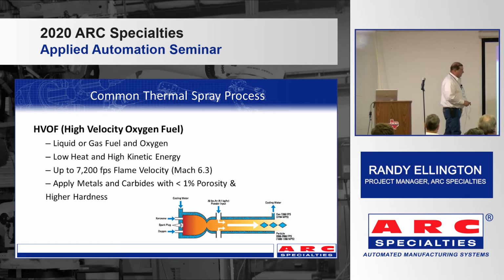HVOF tends to have low heat, and that's a relative term because it's still hot, but it's much less than like plasma. Where that's good is applying stainless steels and Inconels, your corrosion-resistant alloys. You're not over-oxidizing. Same with your carbides. You're not oxidizing the actual material. On the other end, it does have high kinetic energy, so your splats are held together tighter. There's less porosity, higher hardness.